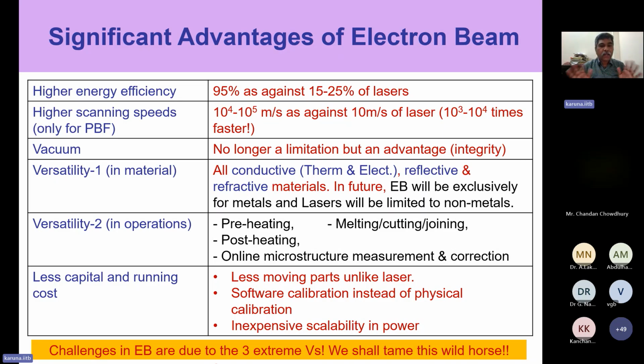But if we take enough masking and protect the people around, it is possible to put X-ray sensors which will predict the microstructure that will come after solidification. Accordingly, you can use this to correct the process parameters. So you can predict the microstructure from the X-ray being emanated and correct it. This is a very beautiful application of electron beam. In my lifetime we won't be able to do it, but I'm sure a lot of people are already working on it. So this is the kind of versatility you get with electron beam.